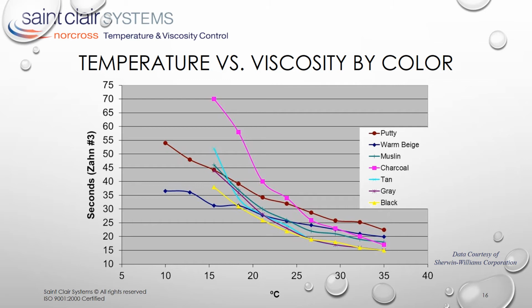We will have to adjust the viscosity by adding solvent, and how much depends on the temperature we're at. Or, we will have to hold each color at a different temperature. The black at 21 degrees C. The muslin and warm beige at 24 degrees C. The charcoal at about 26.5 degrees C, and the putty just north of 29.